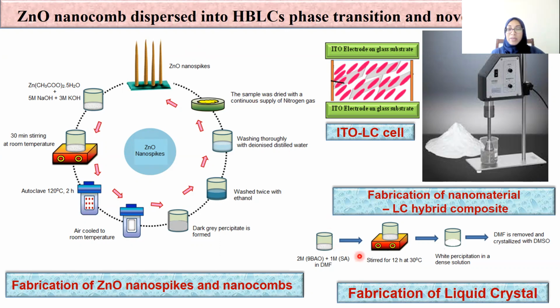And to form the liquid crystal, 2 moles of nonyloxy benzoic acid is added with 1 mole of suberic acid in dimethylformamide. It was continuously stirred for 12 hours at room temperature of 30 degrees centigrade to obtain white precipitation in a dense solution, after which the excess DMF is removed and crystallized with dimethyl sulfoxide.